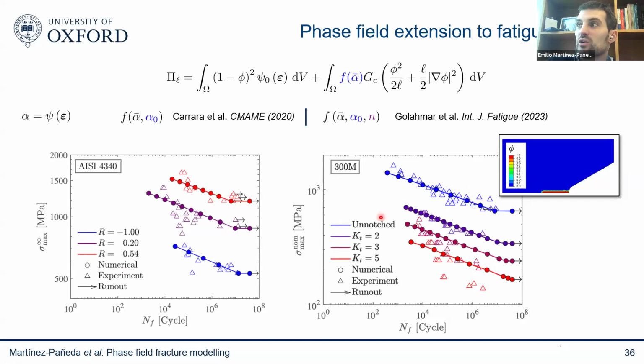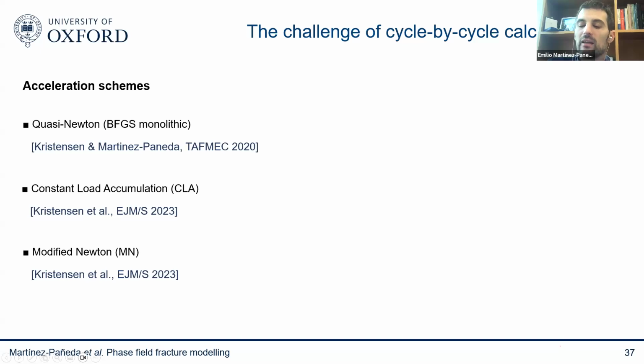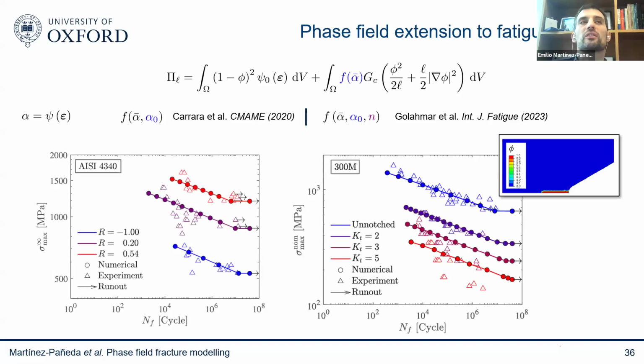And the other advantage, of course, is that you can handle any arbitrary geometry. So here is the SN curve for a sample that is unnotched. There's no crack in there. But then you could add defects of various stress concentrators, and you can see that the model is able to capture this. And this is also of interest for those of you working on computational mechanics, because the beauty of these models is that you're simulating fatigue processes as they happen in reality. So you don't need to make any strong assumptions. You can capture any geometry, any loading history. So, overloads, you can capture anything that you're interested in.